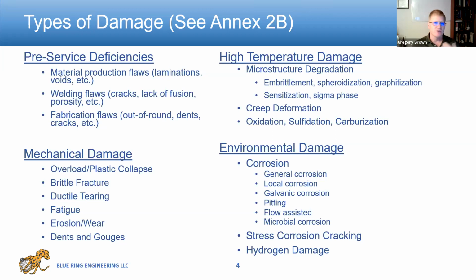Other types of damage, you can have stress corrosion cracking, which is environmental. Hydrogen damage, you can get blisters or cracking. You can get high temperature hydrogen attack. Microbial corrosion, that's when you actually have organisms that are causing corrosion. I always like to imagine little amoebas eating my pipe. That's not really what happens, but it does actually cause metal loss. So 579 allows us to assess most of these damage types and then determine if they can stay in operation.